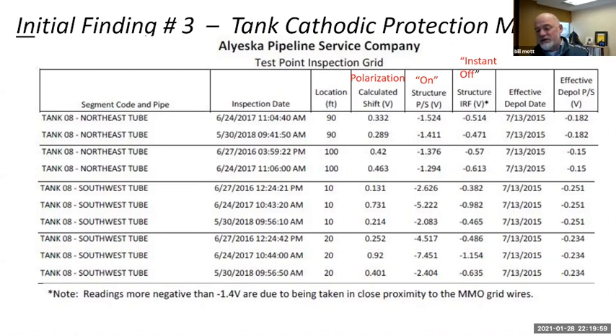So when they say 0.332 volts, like in this reading right here, that's 332 millivolts. So this is what you would use to compare against the 100 millivolt criteria to determine if the structure is protected. Next, column 5, is the on potential. It's not very useful data. It's good for troubleshooting, but not really for anything else. Instant off data is what you would use to compare against the 850 millivolt criteria. That's the IR free or instant off data. Column 7 is the date that the depol data was collected, and column 8 is the depol data.